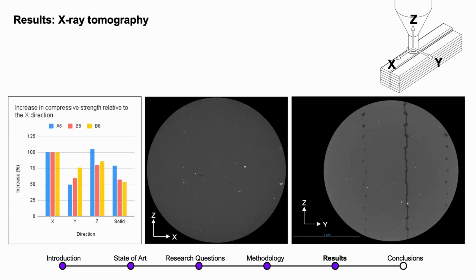If we compare the results with the tomography, we find that these cracks, produced during the drying or sintering process, cause this loss in the compressive strength, but not that much, because we assume that these cracks close under compression. But regarding the flexural results, these cracks do produce a huge loss in the tensile strength, hence this huge difference between X, Y, and Z.